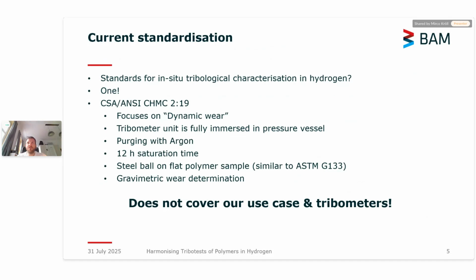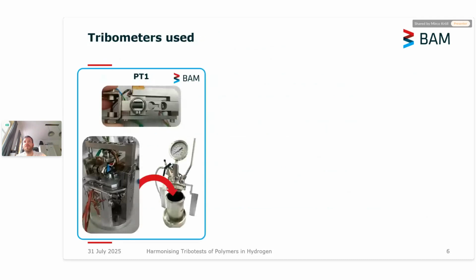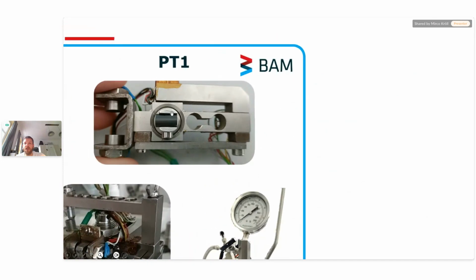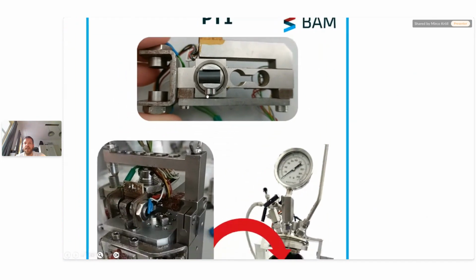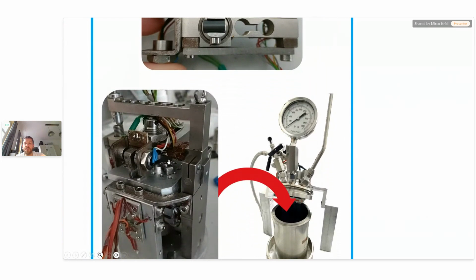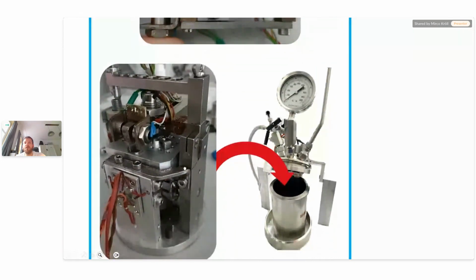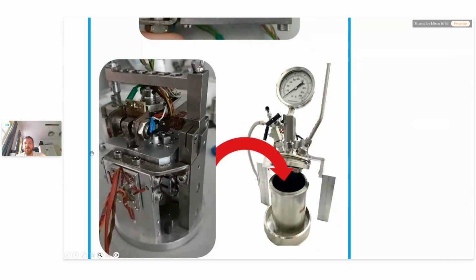And if I talk about tribometers, then I will quickly introduce our stars, so to say. So the tribometers we use. The first one was the PT1 tribometer at BAM in Berlin. This is a high pressure tribometer that is able to test up to 80 bars. You can see here in this arm, there's the polymer sample that is clamped into the arm, and then the arm is put onto the steel disc, which you can see here. And this table is moving in a reciprocating manner so that there's, let's say, the tribological contact happening in between. And this tribometer unit is then introduced into a pressure vessel.